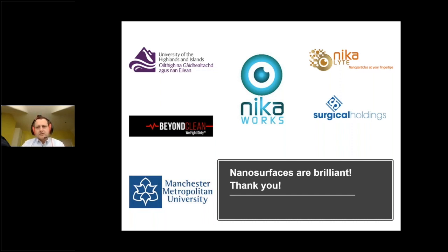Yeah, though the titanium dioxide should be attached very strongly to the titanium nitride. The wear you might be seeing, was it a discoloration you were seeing? Well, I think we've seen other attempts at this sort of coating where it's been multicolored and it just hasn't seemed to last particularly long, unless that's some sort of different electroplating that's colored. But it might not be the same process. Yeah, it's possible to take a physical vapor deposition coating and then you can stick it into electrochemistry and colorize the coating, but you open the door for other problems if you do that.